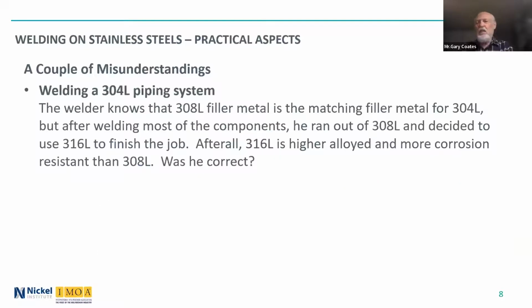So let's take a couple of misunderstandings that I have come across. The first one: the welder knows that 308L filler metal is the matching filler metal for 304L, but after finishing most of the components, he ran out of 308L, and decided to use 316L to finish the job. And after all, 316 is higher alloy. It's got molybdenum in it, a little higher nickel content, and it is more corrosion resistant than 308L. Was what he doing correct?